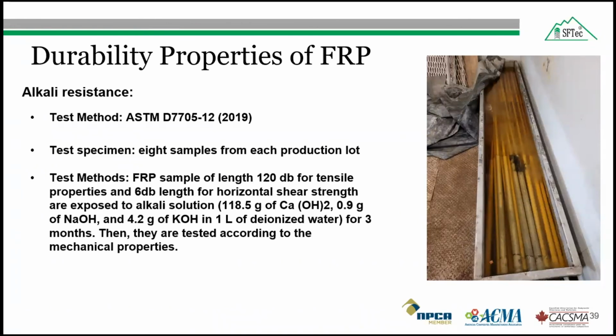The fiber reinforced polymer samples of length 120 times the diameter of the FRP bars are used for the tensile properties, and 6 times the diameter for horizontal shear strength. As I told in the mechanical properties, we use the same length here, and those are exposed to the alkali solution. The alkali solution consists of 118.5 grams of calcium hydroxide, 0.9 gram of sodium hydroxide, and 4.2 gram of potassium hydroxide in 1 liter of water. The exposed samples are kept in the solution for 3 months at a temperature of 60 degrees Celsius. After the 3 months, the samples are removed and tested according to the mechanical properties guidance. For the tensile property, we use the same ASTM D7205, and for the horizontal shear strength, we use the same code as in the mechanical properties.